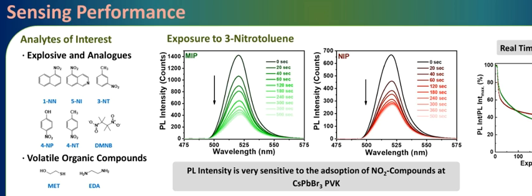As can be observed, the PL intensity is very sensitive to the adsorption of nitro compounds at cesium lead bromide perovskites, in such a way that the PL of the cesium lead bromide polycaprolactone film decreases by around 60% in the NIP sensor and 68% in the MIP sensor when exposed to the analyte for 5 minutes. During this exposure time, no measurable shift of the PL wavelength is observed.